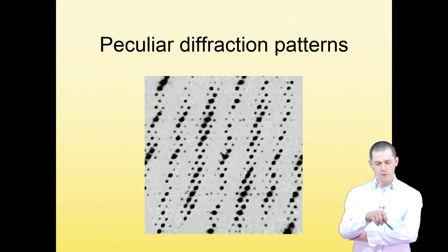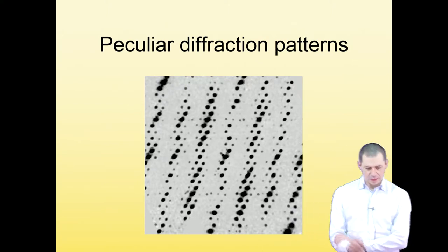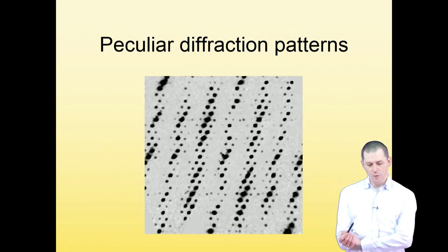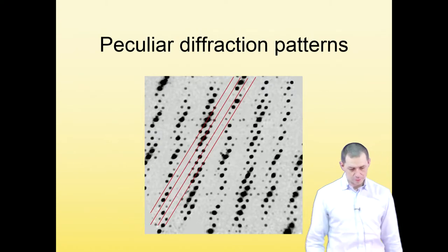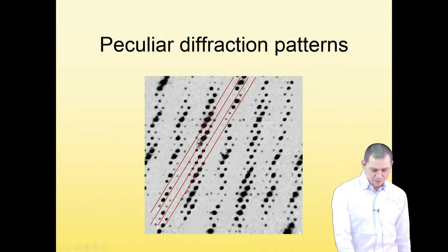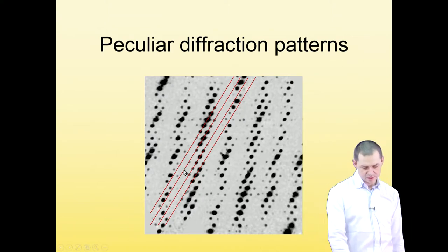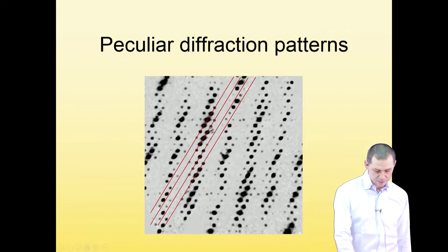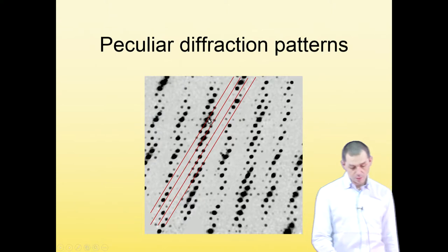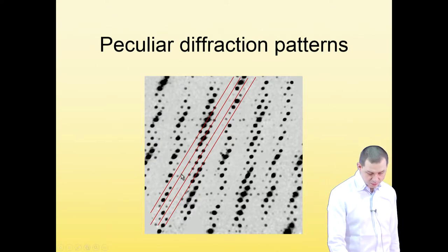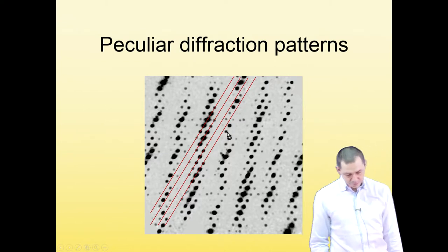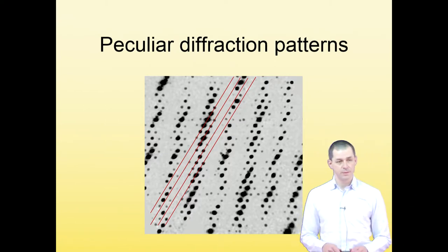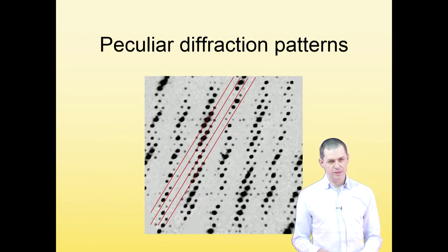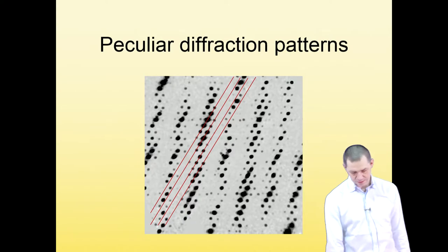So let's focus on this diffraction pattern a bit more closely. At first glance, it seems that it may not be so difficult. There are rows of reflections. And it seems that you could find a lattice that describes the whole pattern, maybe a unit cell like this. But if you focus more closely, you'll see that the line here does not follow in the line here, and it even does not intercept this line in the middle. And it is not possible to find a simple three-dimensional lattice that describes all the peaks in this diagram.